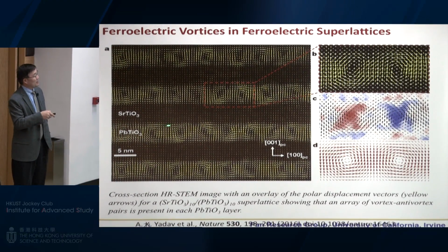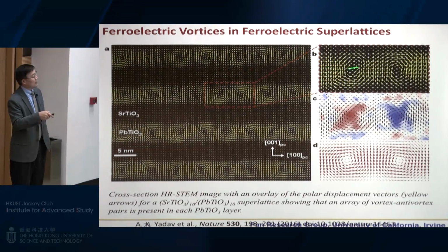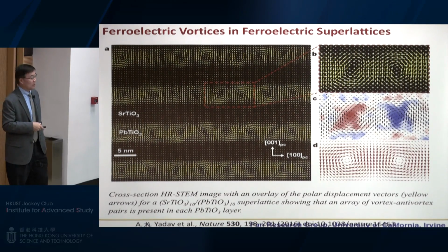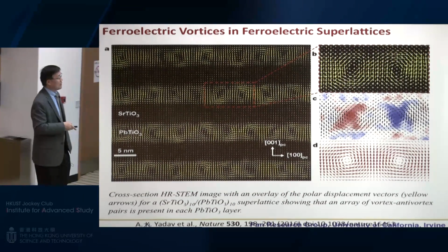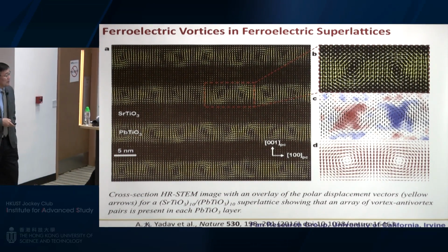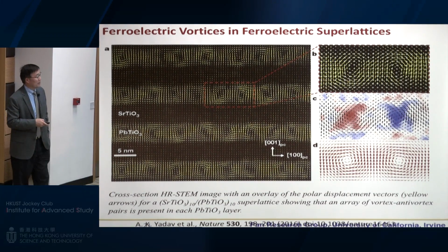So this is an example, right? You see this lead titanate with a very small thickness. Then this is STO, and there's STO and PTO. You see beautiful vortices and anti-vortices in the superlattice structure. This is very nice work and creates new physics in this ferroelectric system.